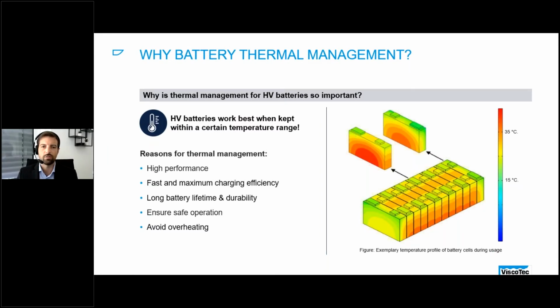So why is thermal management of HV batteries so important? There is a very simple answer: because HV batteries work best when kept in a specific temperature range. Theoretical values are within 15 to 35 degrees Celsius. But what does it mean, work best? That means the ability to manage heat during charge and discharge cycles is crucial for high battery performance. And furthermore, it is very important to keep the core components of electric vehicles at temperatures that facilitate maximum charging efficiency, durability, and maximum driving range. And finally, most important, because of safety reasons, we need to ensure a safe operation, which means to avoid overheating of the battery system and finally to protect the passengers. Next slide, please.